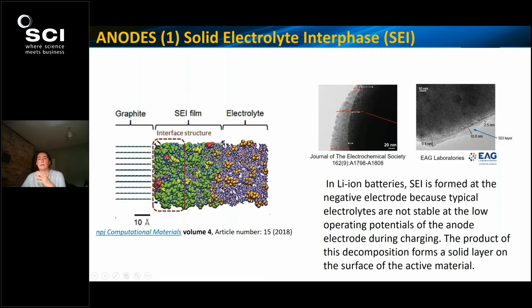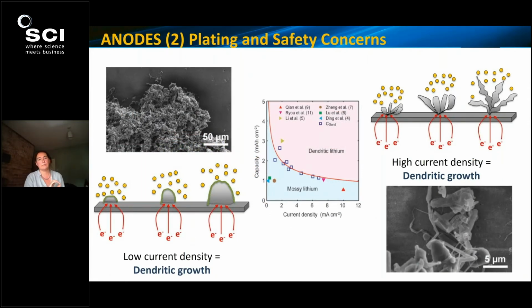You get this very interesting combination of inorganic and organic phases, which irreversibly consume a ballpark of about 10% of your lithium, which acts as a charge carrier. So it's a partial reduction in the lithium inventory, which causes an initial hit on the capacity. This is what you can see here on the left. And in the TEM cross-section images on the right, these passivating layers are of nanometer dimension. They're quite thin and not always continuous. It's very important that they passivate the underlying active substrate to stop it further reacting with decomposing electrolyte, but they have to remain ionically conductive so that the lithium can convey charge in and out of the active materials. So that's the first degradation mode of the anode, in that it uses up some lithium irreversibly.